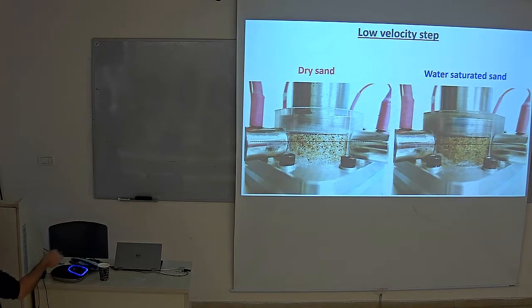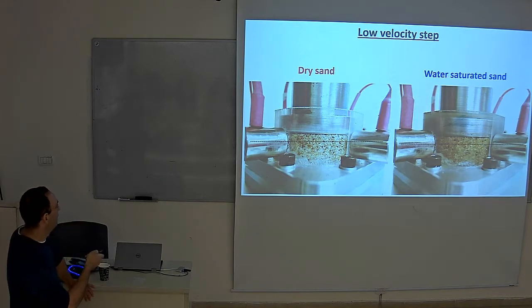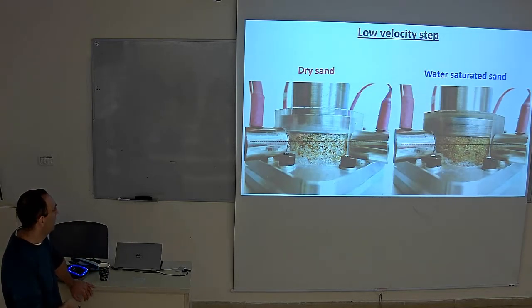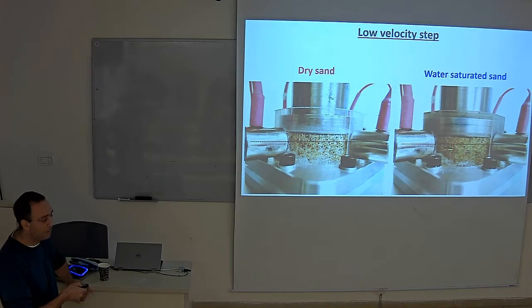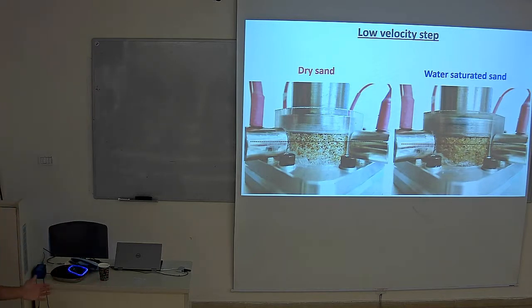So this is a dry experiment, this is a water saturated experiment. I'm shearing the system at low velocities. It's slow motion of the experiments, not real time. And I think there is not a big difference between them. This is a line that I put to show where is the base of the shearing grains. Personally, I don't think I see any big difference between the experiments. So this is for the low velocity.